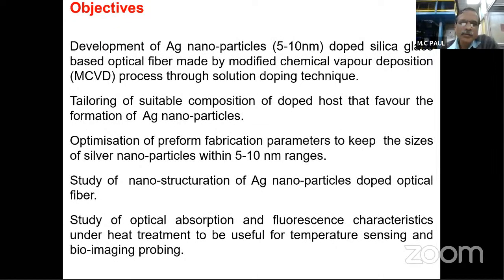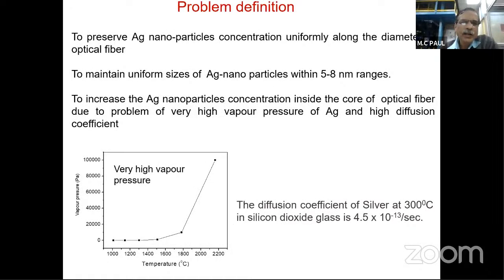The objective is development of silver nanoparticle doped optical fiber by MCVD solution doping technique and tailoring of the composition of this glass so that the silver nanoparticles sustain a particle size within 5 to 10 nanometer, so that the loss of the fiber becomes very low. The tuning of the spectroscopic property with increasing temperature gives rise to red shifts of the optical absorption and fluorescence characteristics that can be useful for temperature sensing and bioimaging probing.